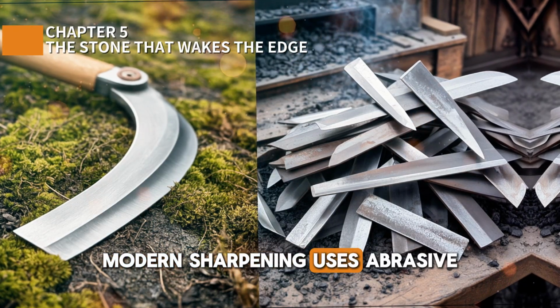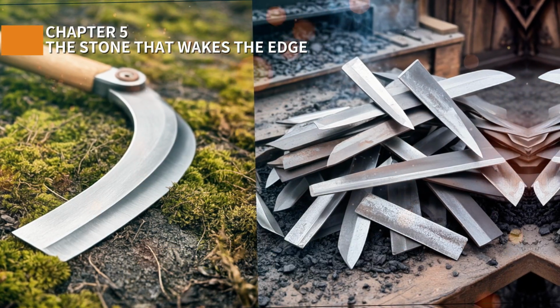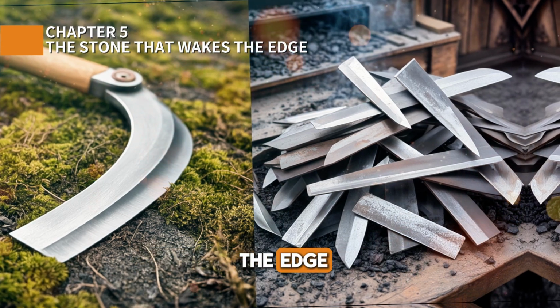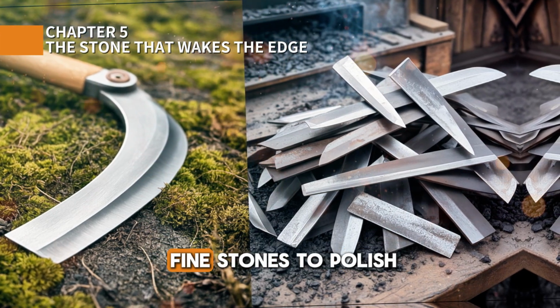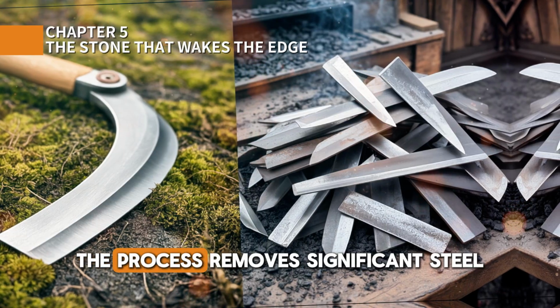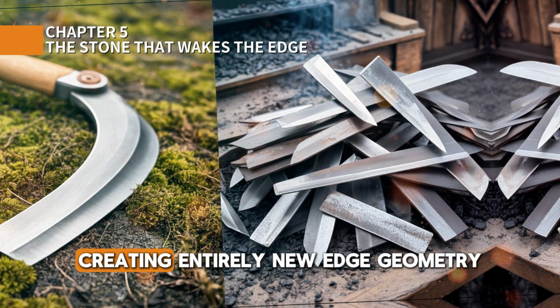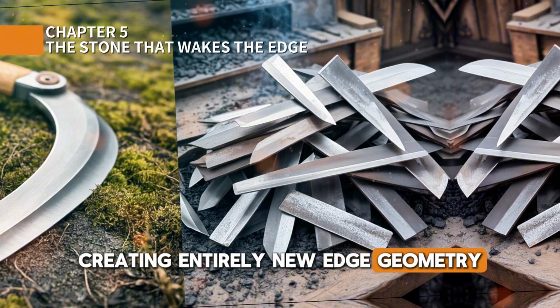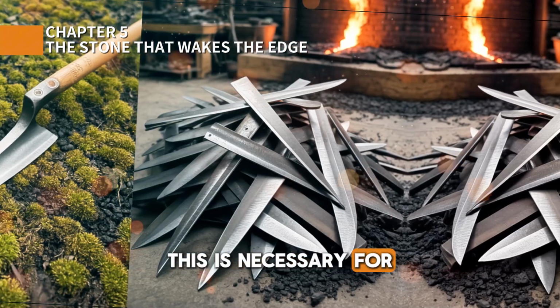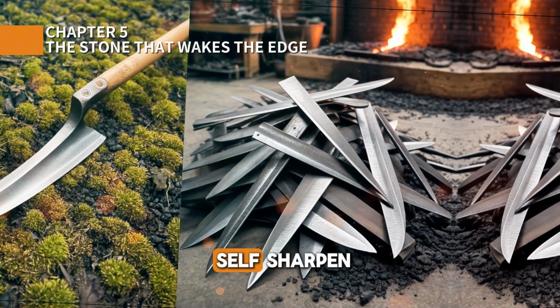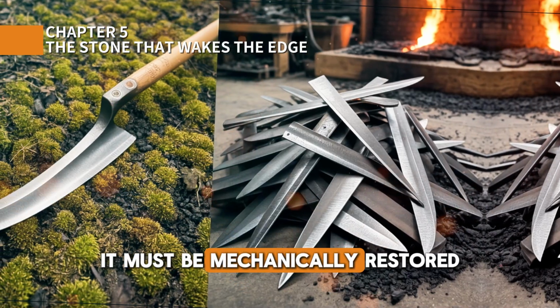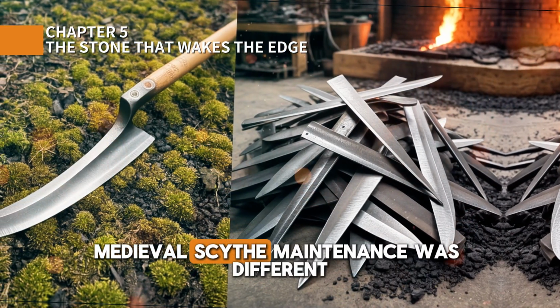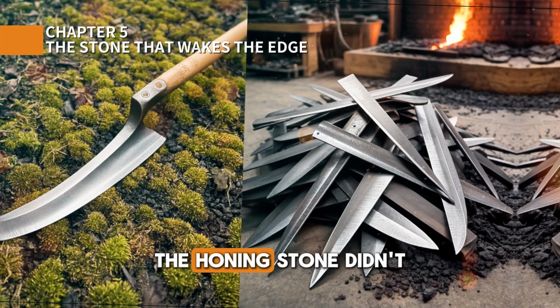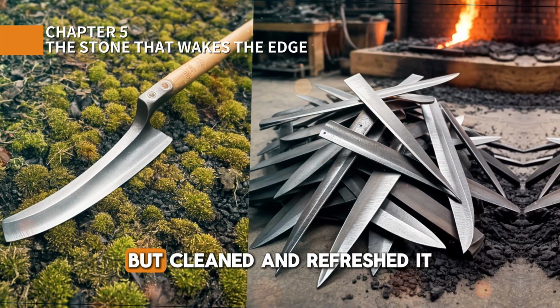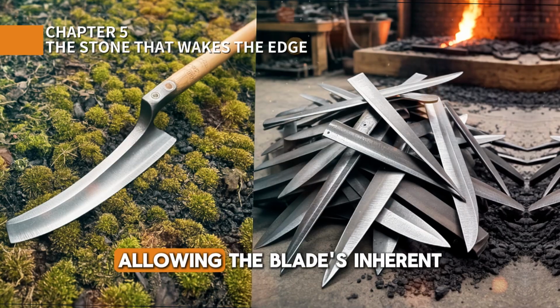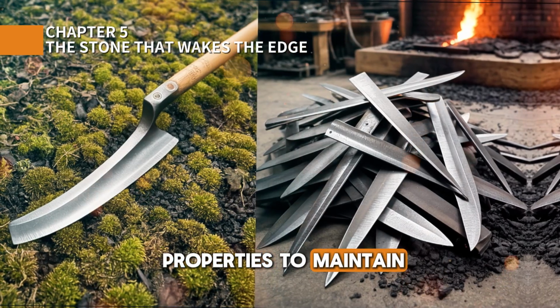Modern sharpening uses abrasive materials in sequence: coarse stones to reshape the edge, medium stones to refine, fine stones to polish. The process removes significant steel, creating entirely new edge geometry. This is necessary for modern knives because the steel cannot self-sharpen. It must be mechanically restored. Medieval scythe maintenance was different. The honing stone didn't reshape the edge, but cleaned and refreshed it, allowing the blade's inherent properties to maintain sharpness.